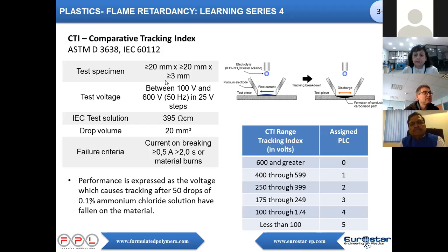So the test specimen is standard. The test voltage is between 100 and 600 volts. It cannot be chosen by chance. There are steps. Basically it's 175, 250, 300, 375, 500, and 600 volts, which are the most common. The electrolyte solution can be checked by conductivity. The drop volume has to be calibrated, and this is a very, very tough point of this measurement.